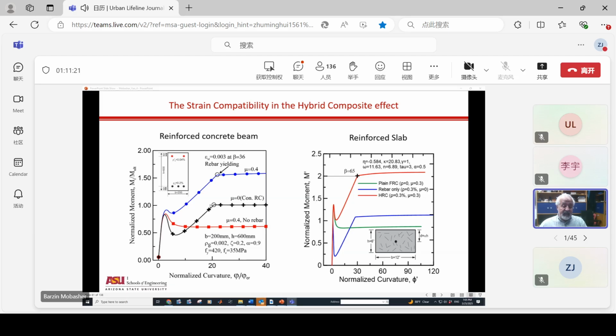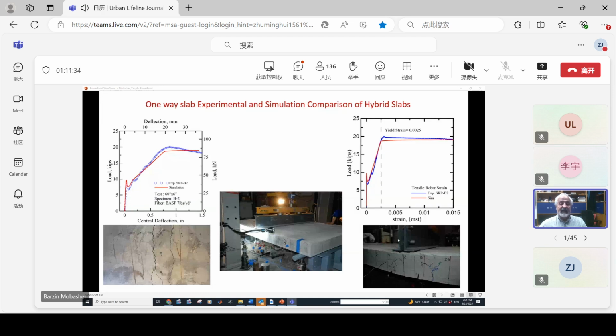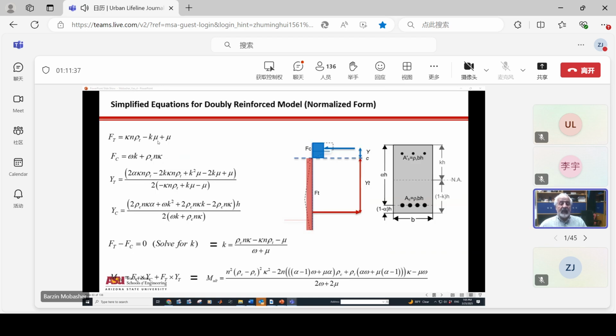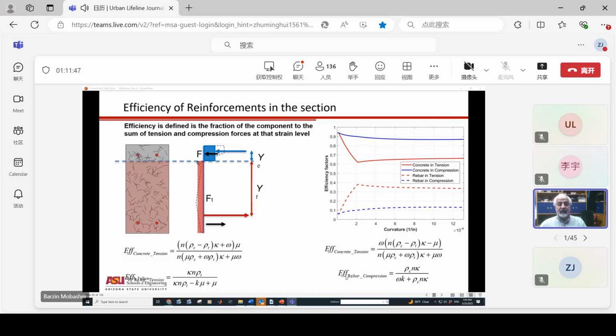We still need steel rebar, but if we add it with fibers, all of a sudden we get this synergy that the load on the steel is significantly reduced and the fibers carry the load. And we've shown that with panel tests. And again, we can calculate simplified equations, very simple equations that for undergraduates can be done in a spreadsheet. All of the parameters can give us the efficiency of the system in the section, in tension or in compression. And we can see that now we're getting a lot more load out of the concrete.